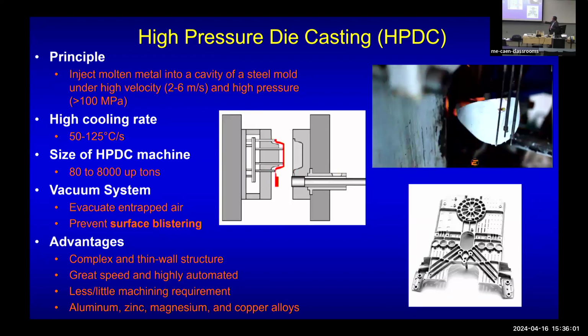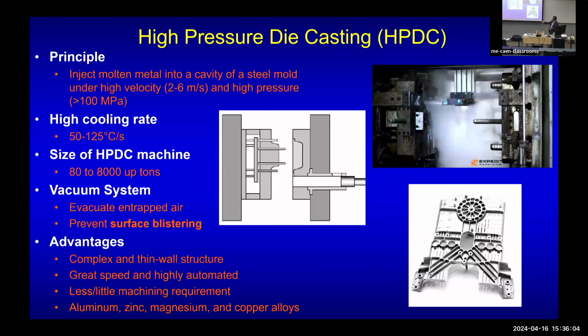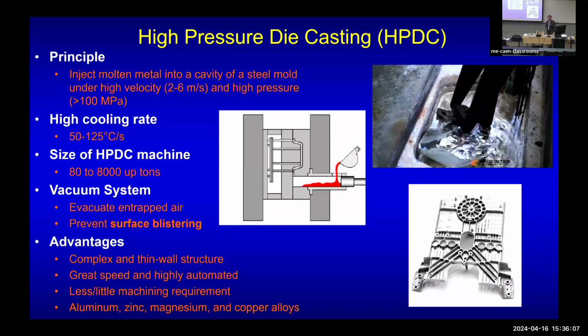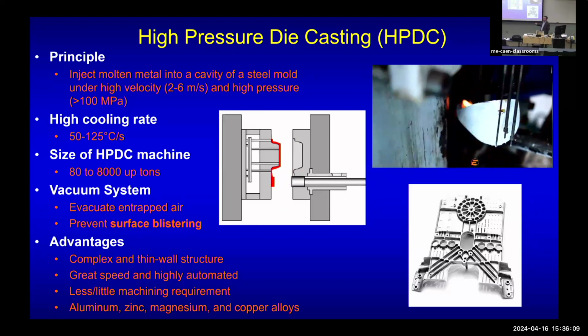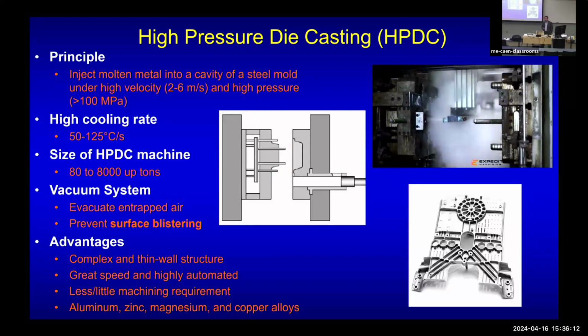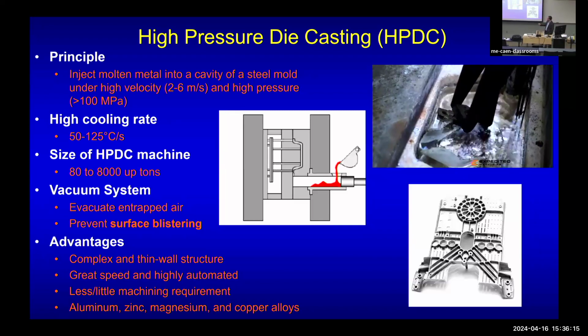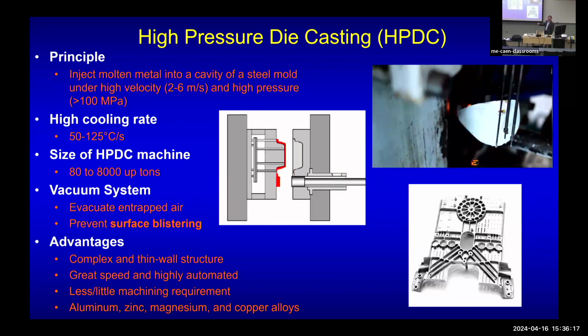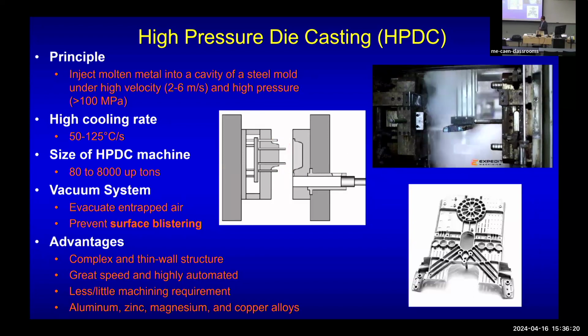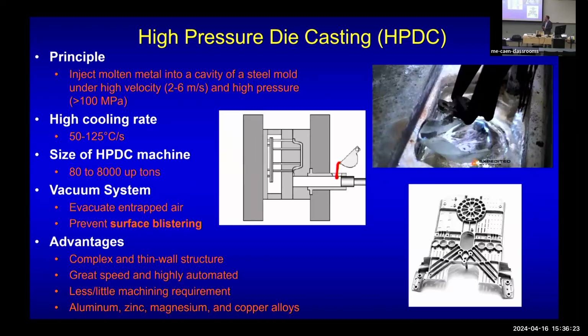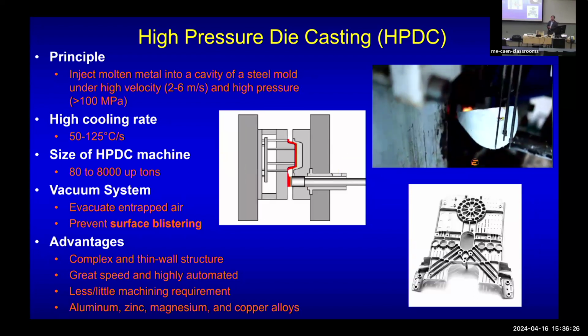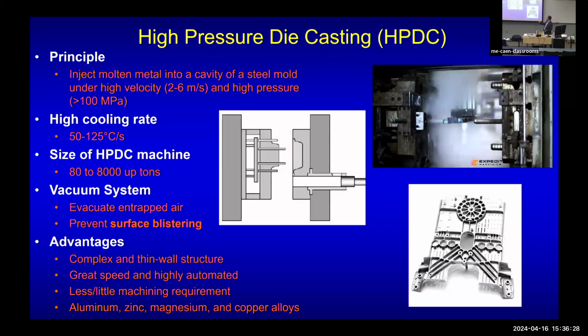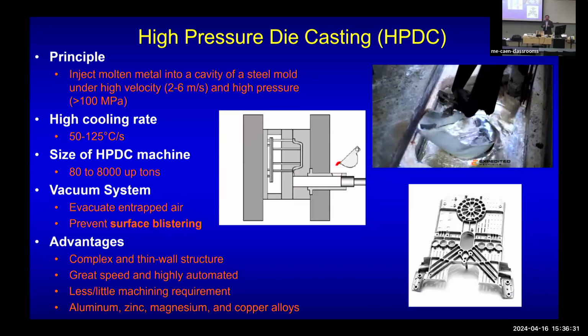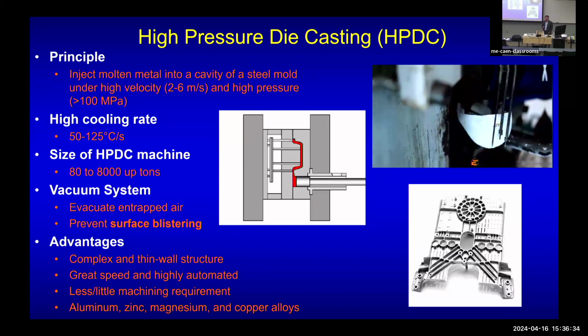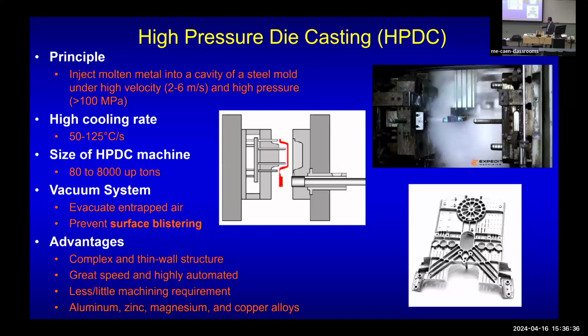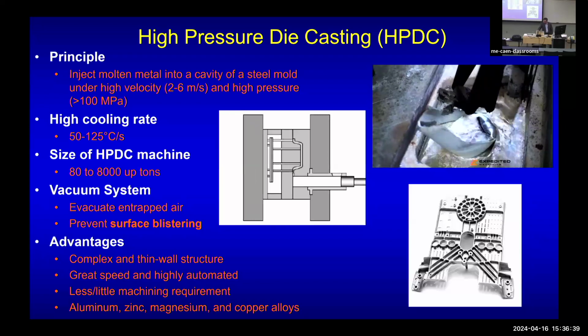Right? You have molten metal feeding here, and quickly ejecting into the die at meters per second, very high speed. And they talk about cooling rate, about very high cooling rate, 100 degrees C per second. And then the machine can be 80 to 8,000 tons. And today they go to more than 10,000 tons now, right? And that's a machine with very high speed, very highly automated. A lot of consumer electronics and the automobile industry rely on this process a lot, right? To make low-cost and high-performance components. Especially focused on aluminum, zinc, magnesium, and copper alloys.